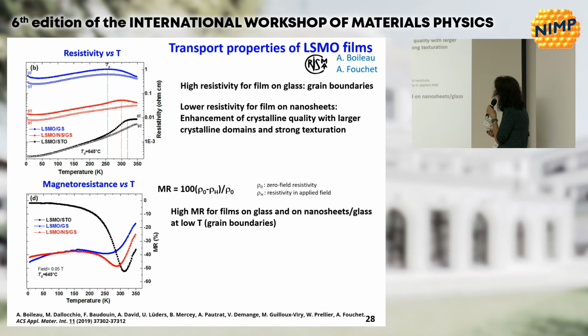Now, if we look at the resistivity as a function of the temperature under a field or without a field, we see here the reference on single crystalline substrate, and here the material on glass, and in the middle we have something intermediate for the material on nanosheets. And this is due actually to the fact that you have no ordering in plane, so we have a lot of grain boundaries in the material. And finally, concerning the magnetoresistance as a function of the temperature, this time we see that the material directly deposited on glass and on nanosheets are very close to each other, and you have a very strong magnetoresistance response, again thanks to the grain boundaries we have in the films.